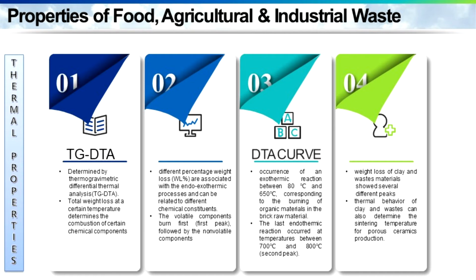This is because most organic porous materials cannot withstand high temperature. However, typical inorganic materials such as glass wool and rock wool are fragile and hazardous to health. The last endothermic reactions occur at temperatures between 700 and 800 degrees Celsius. In addition to the degradation stages for the organic components, the thermal behavior of waste materials can also determine the sintering temperature for porous ceramic production. Well, the low firing temperature for the production of waste-based porous ceramic indicates significant energy saving.